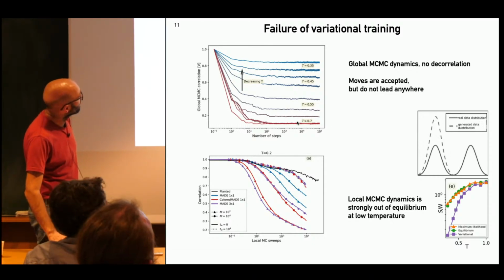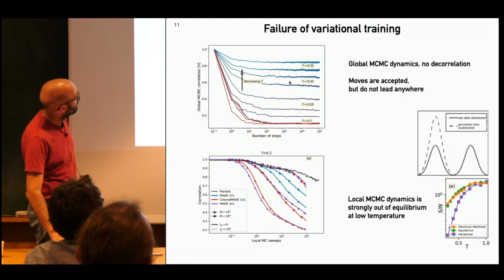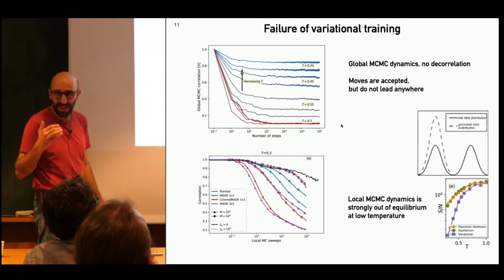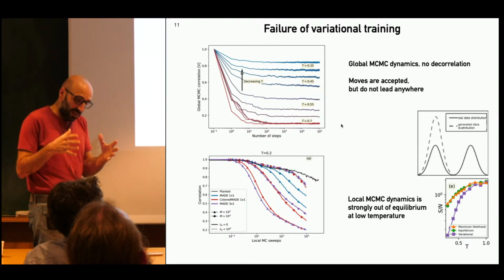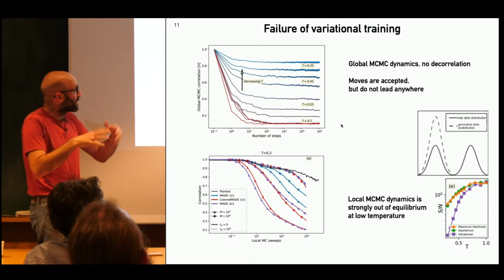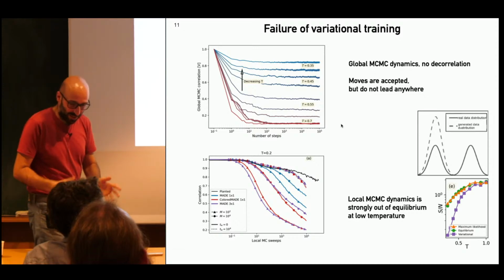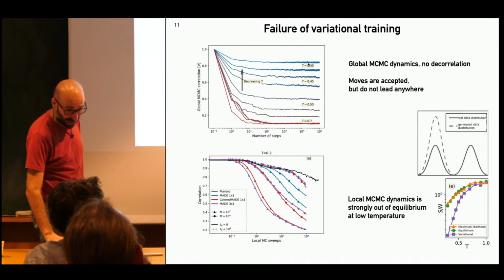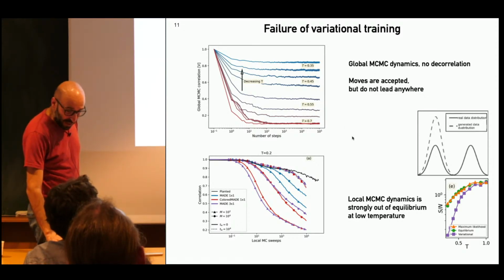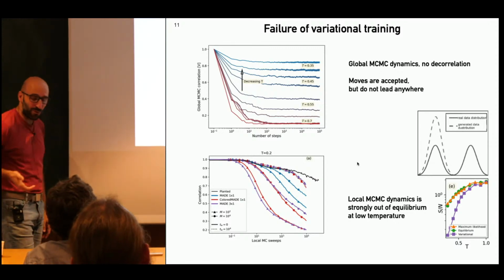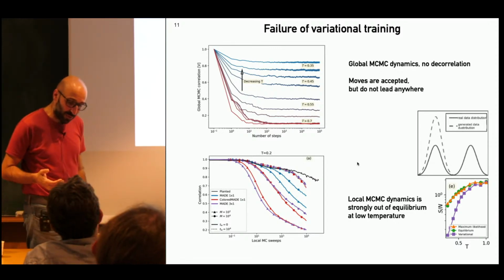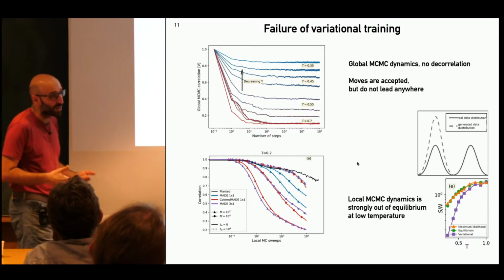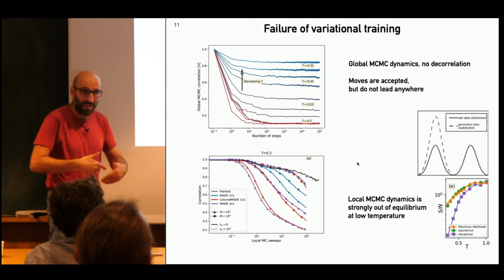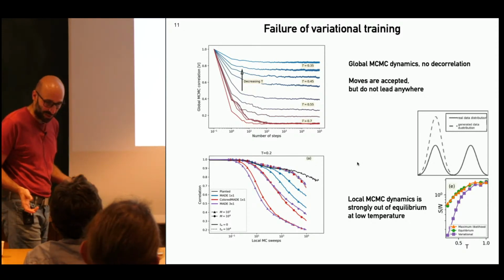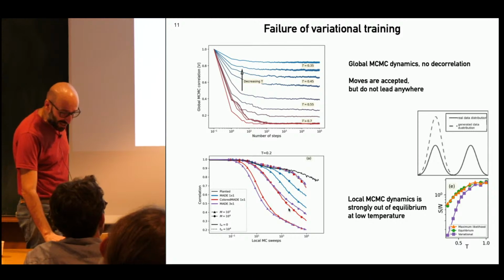So you see at high temperature it works, but when you go low in temperature, still quite higher than the glass transition, you propose moves that are only in some subset of the space, and so the correlation doesn't decay anymore. And also, you could say, maybe I cannot use it for global MCMC, but maybe I can still use it to generate configurations that are close enough to equilibrium that I can at least get some idea of the equilibrium dynamics. But even that doesn't work.